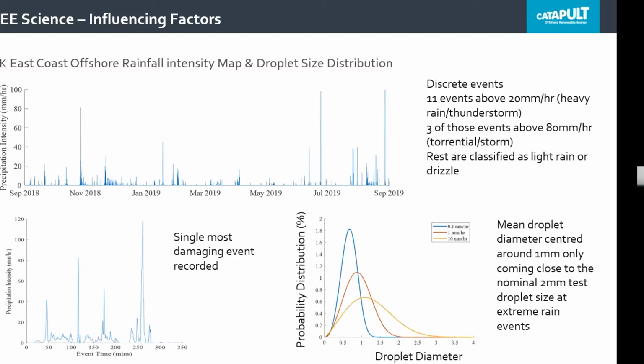The other thing to point out is that your droplet sizes change depending on your rainfall intensity. On the bottom right, this is a probability distribution, measured from our offshore data. The mean droplet diameter is actually around 1 millimeter and not the 2 millimeters that has been used in tests. Only in the extreme events would you come close to that 2 millimeter droplet size. So the way we're currently testing is not representative of what's happening offshore, and this is an active area of research.